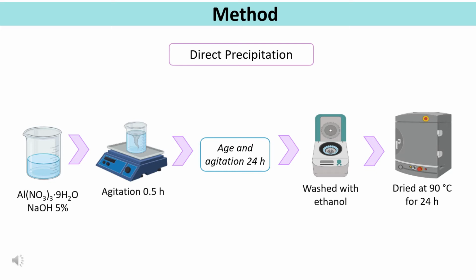Continuing with the methods, the chemical reagents were analytic grade and used without any further purification. For the direct precipitation method, we prepared an aqueous solution of aluminum nitrate with 5% sodium hydroxide, then agitation for 0.5 hours, sequentially aged, and agitation for 24 hours. The resulting solution was centrifuged and washed with ethanol. Then the solid was dried at 90 degrees Celsius for 24 hours.